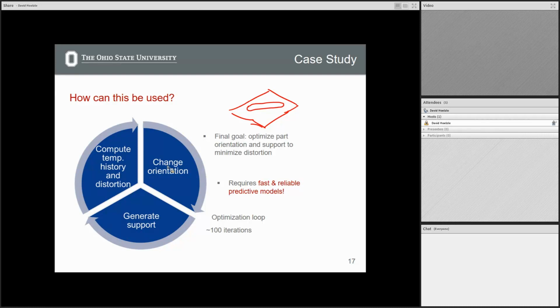So what that means is you're using these loops where you at first randomly choose an orientation, you generate support structure from that, and then you compute what primarily we're mentioning, what is the distortion, right? And so then you can say, all right, now given this distortion, I can change the orientation. And we were using a somewhat random way of going around the entire 3-dimensional angle space to do this, and to then continually go around this loop until we converge to some sort of orientation that is optimal with respect to an objective function that weights distortion.